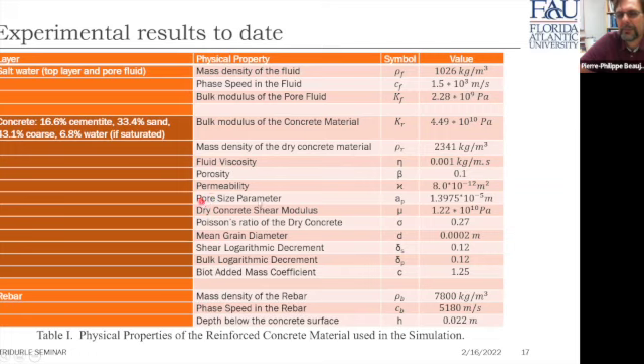In addition, we also model the pore size parameter, which I explain a little later, the dry concrete shear modulus, the Poisson ratio of the dry concrete, the mean grain diameter, and we also account for 3 other parameters, which are the shear logarithmic decrement, the bulk logarithmic decrement of the wave, and the Biot added mass coefficient, which accounts for the mass loading of the skeletal frame by the fluid. In the rebar, we model the mass density of the rebar, the phase speed in the rebar, and the depth below the concrete surface. So all these parameters were in the results I'm showing here.